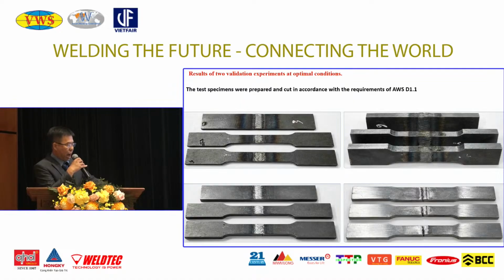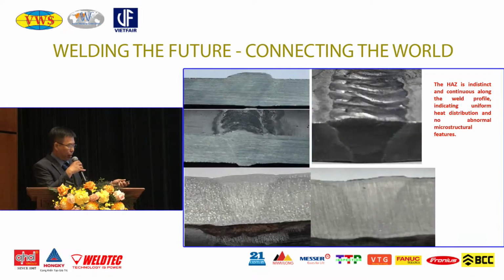This slide presents the experiment and preparation of specimens for evaluation. After welding, the sample was cut and prepared for further testing and analysis. This slide shows evaluation of the heat-affected zone. The HAZ is consistent and continuous along the weld profile, indicating uniform heat distribution and no abnormal microstructure features.